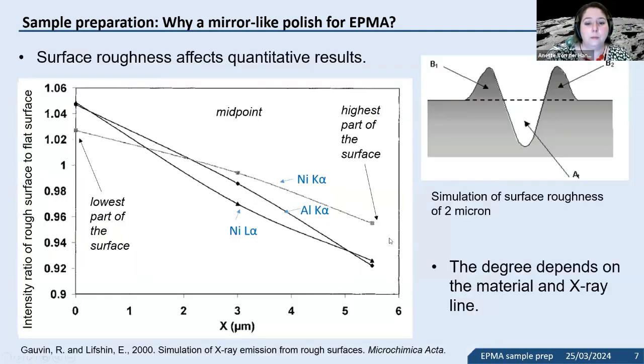To give you a bit more of an idea of how that looks, this is a really nice paper on Monte Carlo simulations where they looked at rough surfaces. The case I show here is a surface roughness of 2 microns, so almost the final polish that we want. What you see is the intensity ratio relative to a polished surface. At 1, you would get exactly the same intensities as a polished surface, and then you can lose down to 8% or have higher values up to 5, depending on the topography.